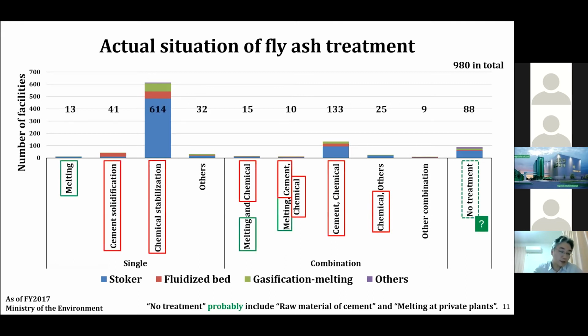This figure shows the actual situation of fly ash treatment over Japan based on statistics by the Ministry of the Environment. As of 2017, as many as 980 thermal treatment plants, including incineration and gasification, are working in Japan. The number of facilities doing chemical stabilization, red line box, or a combination of chemical stabilization and cement solidification is overwhelming, nearly 80% of the total.